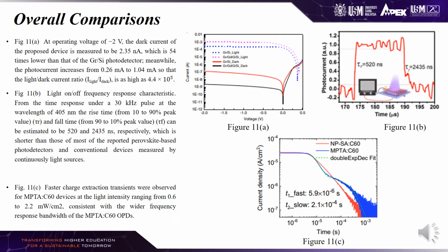While figure 11c shows the faster charge extraction transients were observed for MPTA carbon-60 devices at the light intensity ranging from 0.6 to 2.2 milliwatt per centimeter square, consistent with the wider frequency response bandwidth of the MPTA carbon-60 organic photodetectors.